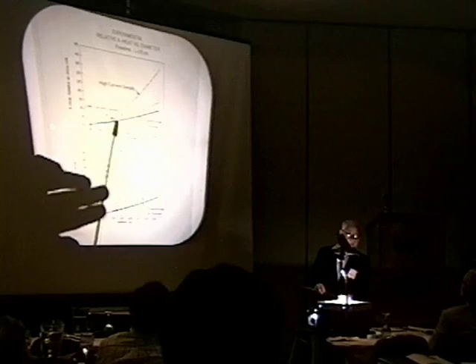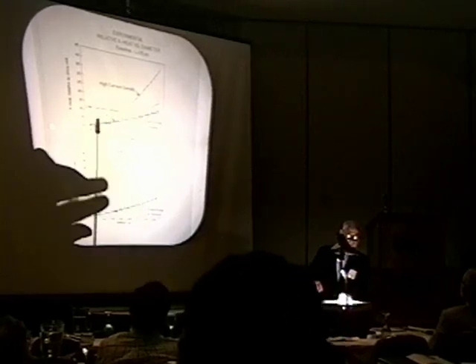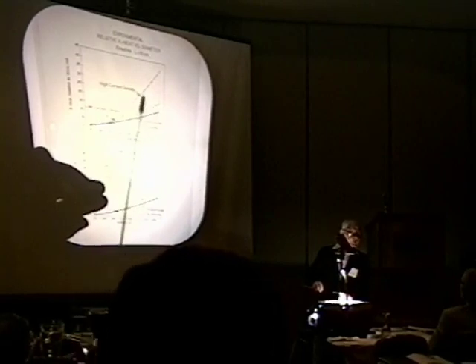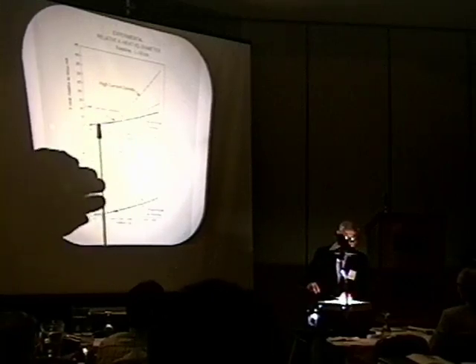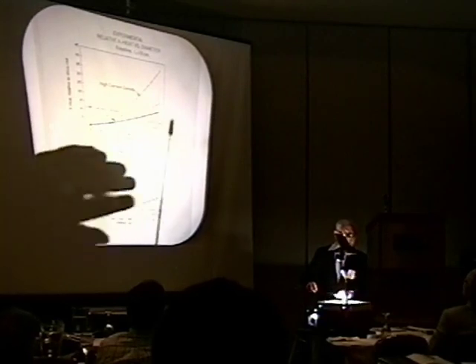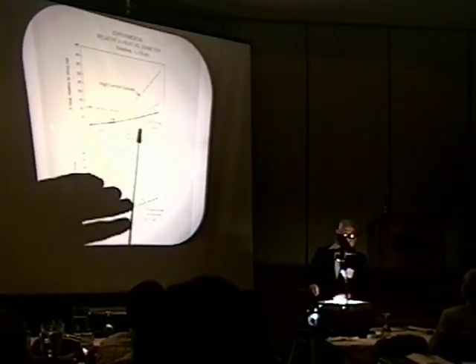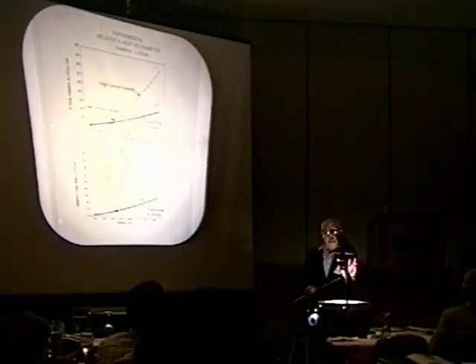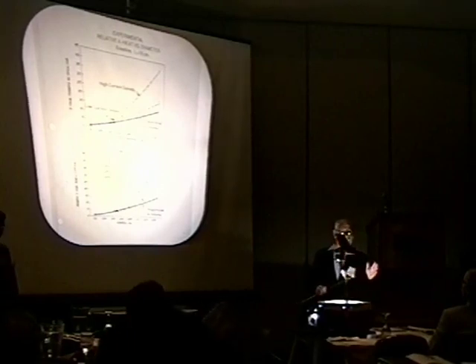This dark line is a calculated line where we plotted against diameter the position the X heat would have if it were exactly proportional to the volume. If it were exactly proportional to the surface area, on the other hand, it would be a straight line down here. Now, obviously, none of these points get anywhere near the proportionality for surface area. So one is almost forced to the opinion that in this case, this is a bulk effect.